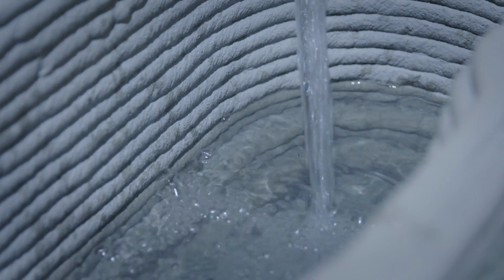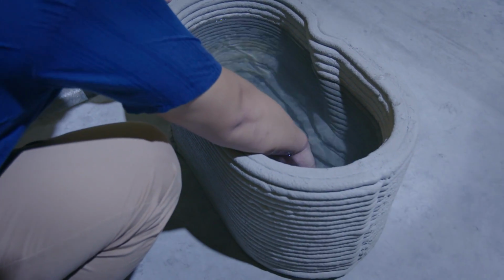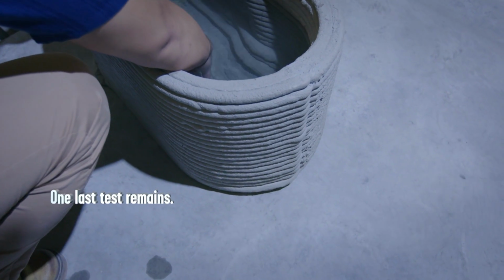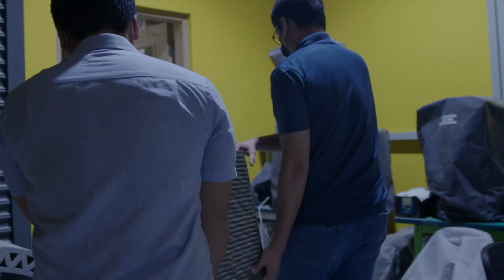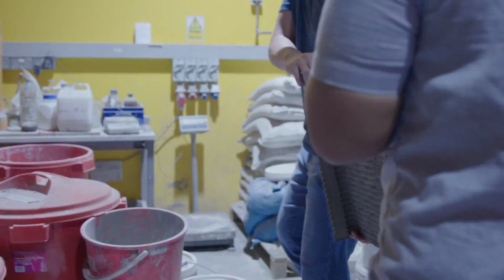We're able to prove that the printed part is able to have a good buildability. There isn't leakage between the filaments. To find out whether the test passes or fails, if there's water retention in the wall, the specimen will actually be heavier than the specimen that's not being tested. So with the new composition of our material, the specimen that we've tested has passed the test.